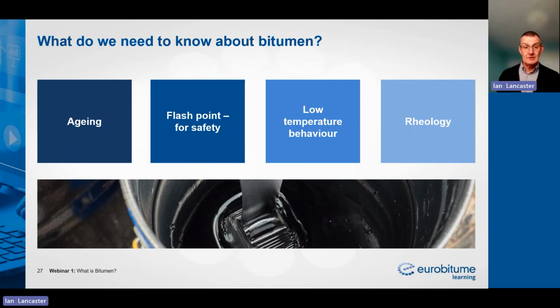Or we can carry out long-term aging, where we can try and simulate the aging that bitumen experiences in an asphalt material throughout its lifetime. We also need to know about the flash point of the bitumen. Is it safe to handle? At what point will the bitumen potentially catch fire? And we can measure that temperature, and from that we can then establish suitable mixing and handling temperatures to ensure that we don't approach the flash point of the bitumen.